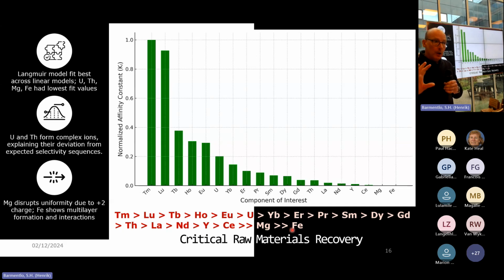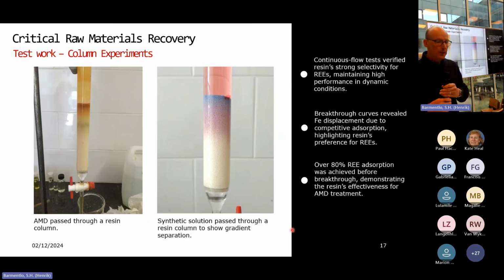So now we know what's the right order to strip these things out, what's the right resin, how do we do this? And we then went on to these column experiments. So we pass our acid mine drainage through a resin column. This picture on the right is not real. It is real, but it's not AMD. It just shows you how you can get these chromatographic separations through these resin beads as you start to strip things out and they absorb.